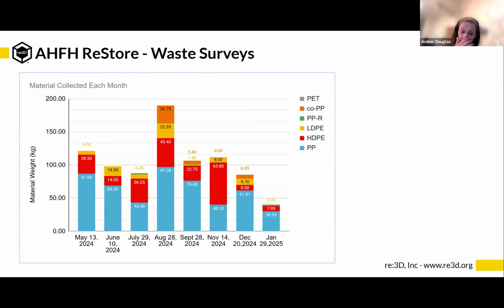So every month, me and Chris go to the ReStore, and we go through all their waste, and we have right here the survey of what we get. And so you can see that polypropylene is the highest amount of material that we get, and so we focus most of our work on that. But all the other polymers that we were picking up are pretty much polyolefins as well, except for the polyethylene terephthalate right there. So they have a lot of polymer that they can print with, and we've had a lot of polymer to play with to practice.